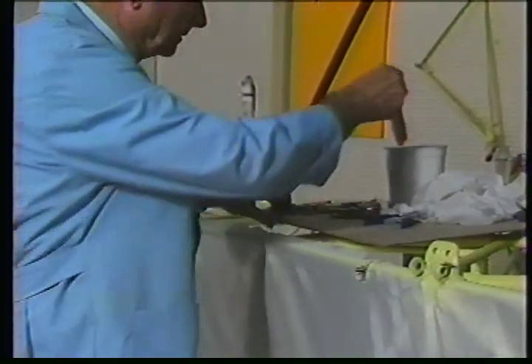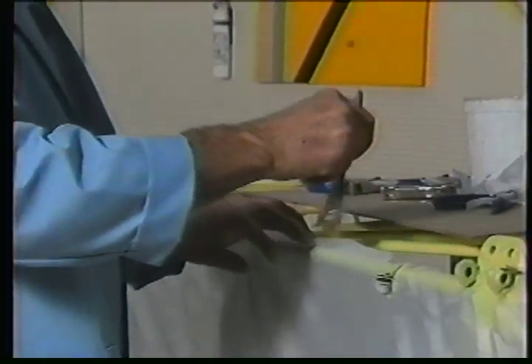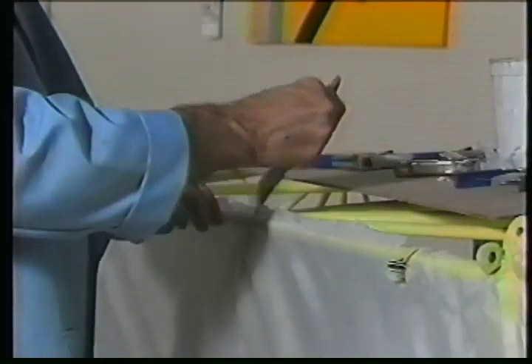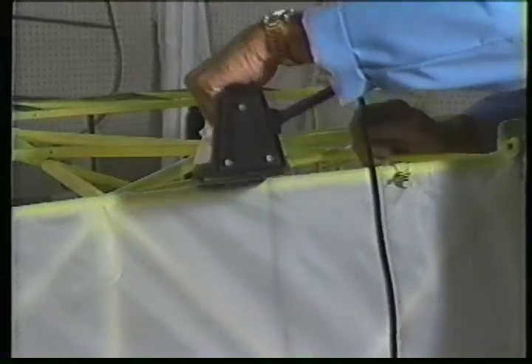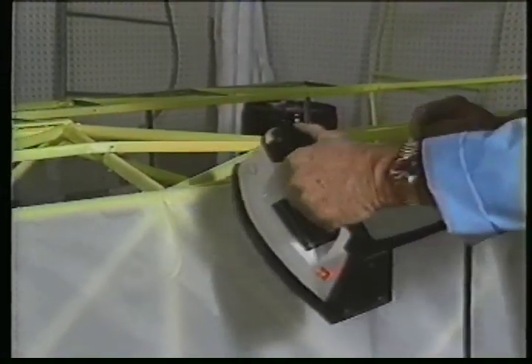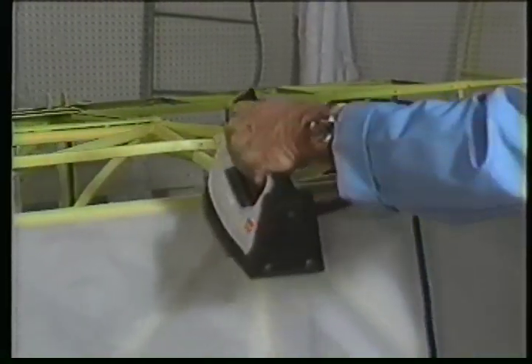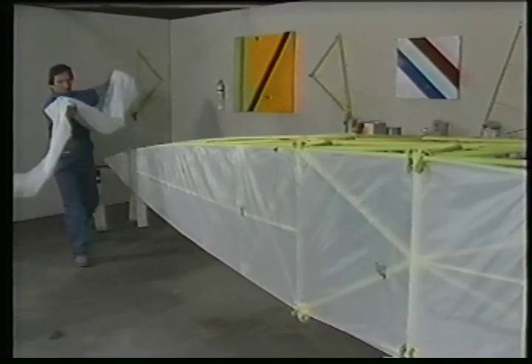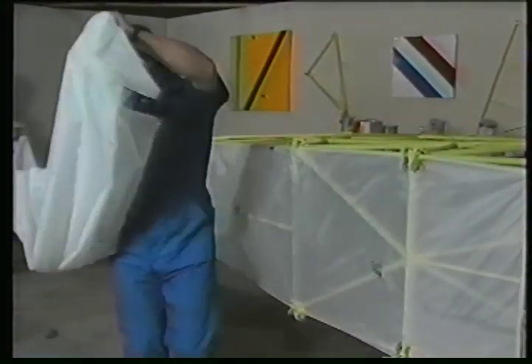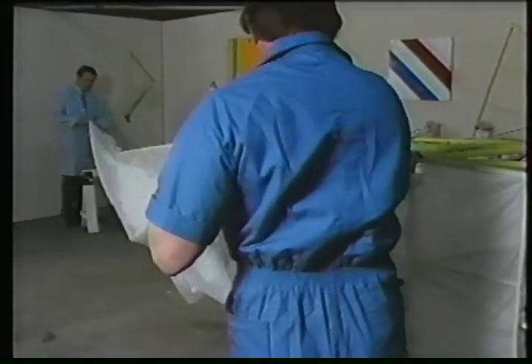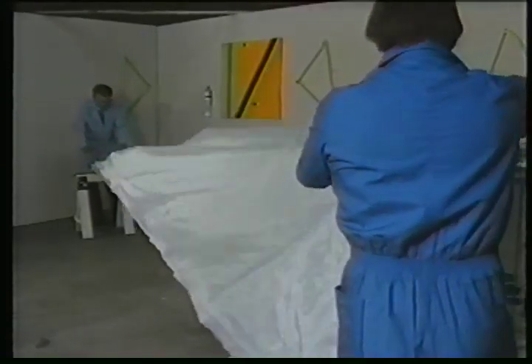Next, roll the fuselage on its left side and trim off the excess fabric and roll the edge around the tubing and cement it into place. After the cement is dried about 10 minutes, we can use the iron at 250 degrees to remove any wrinkles which may show when the next piece of fabric is installed. Next, take the fabric trim from the left side and reverse the end and cement to the right lower and top longeron, the same as the left side, using the same procedure.